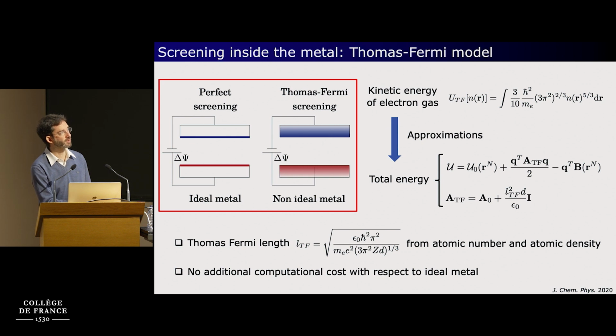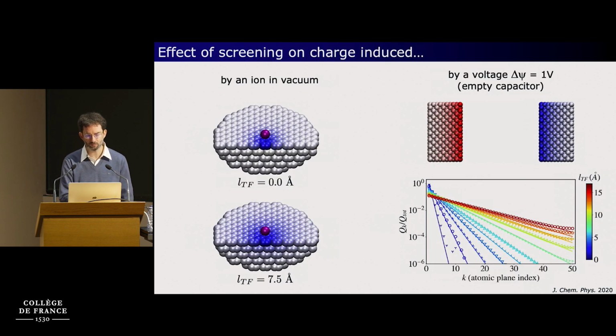additional term on the diagonal, which involves this Thomas-Fermi screening length, L_TF, and also the local atomic density inside the electrode. And this Thomas-Fermi screening length depends on the atomic number of your electrode atoms and again on the atomic density. And the good news is that this additional feature of the model comes at no additional cost, because you can use exactly the same algorithm as before to include the metallic character.